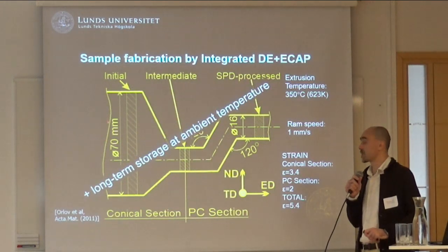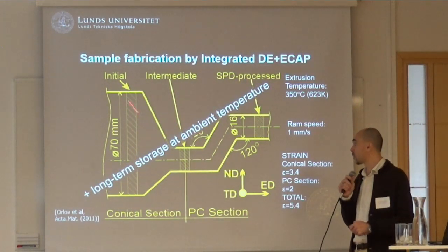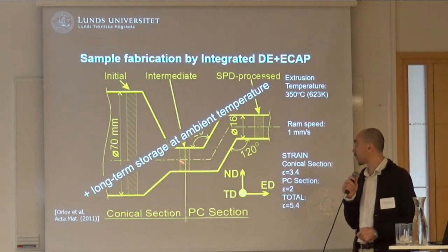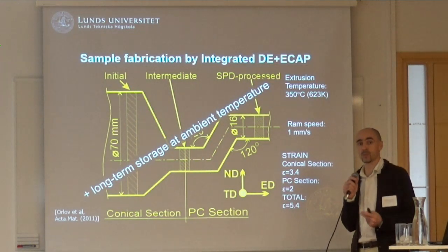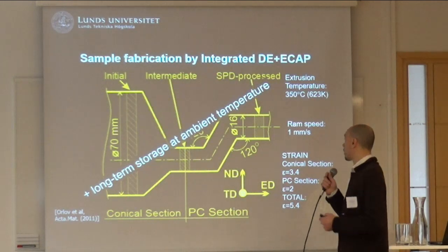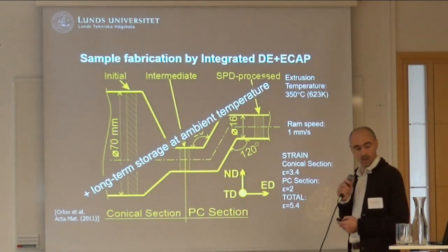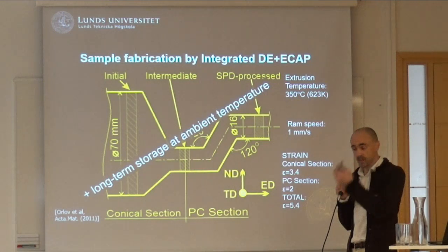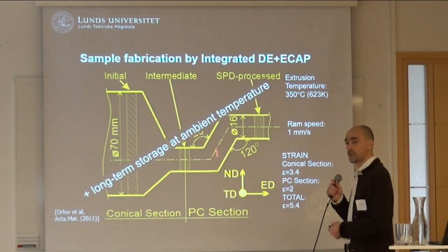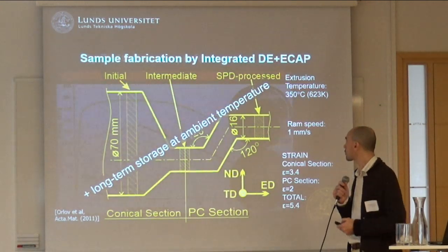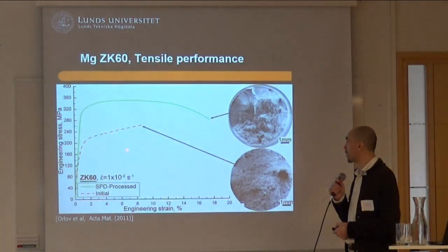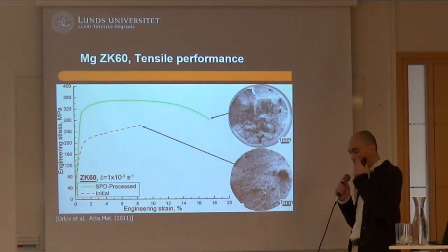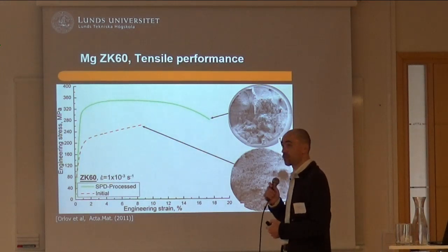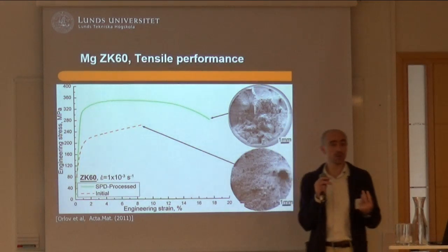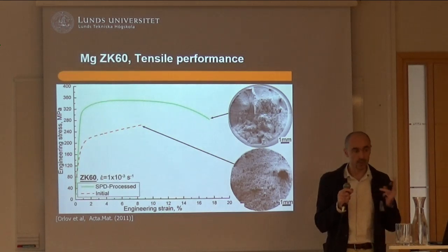So that is extrusion technology. When you have a round bar, in this case it was 70 millimeter, and then in one go, we have a conical die, and then it goes with this bend channel, with a parallel channel extrusion, right? Then we accumulate much larger strain in our material. We managed to produce 4 meter long bars in one go. From the initial material condition, which was just a hot extruded state, we got improvement of both strength and ductility because of controlling 2 main parameters.